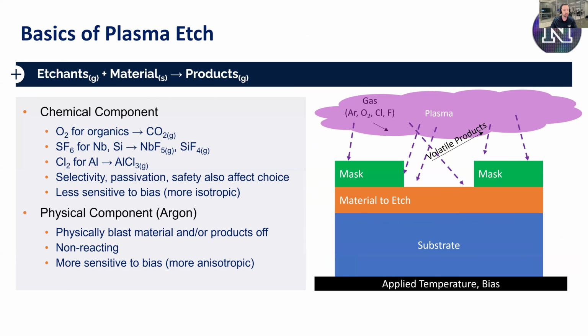That could be a chemical etch. So if you're talking about just photoresist, you're ashing with oxygen in a plasma, it produces radicals, and those very, very reactive radicals will form CO2 and water. Great. SF6 does similar work with niobium and silicon. For instance, you can get niobium pentafluoride, I guess, and SiF4. You can get these products that are volatile. Awesome. Chemical etches, you have to worry about selectivity, passivation, safety. Obviously, chlorine can be a bit dangerous.